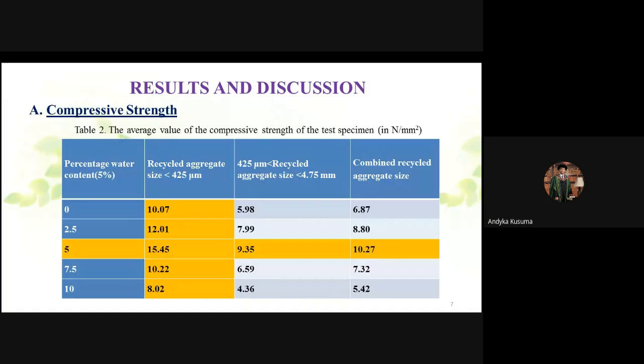Thereafter there was a reduction in compressive strength, and the maximum compressive strength was obtained with 5% water content and for particles having sizes below 425 micrometer.